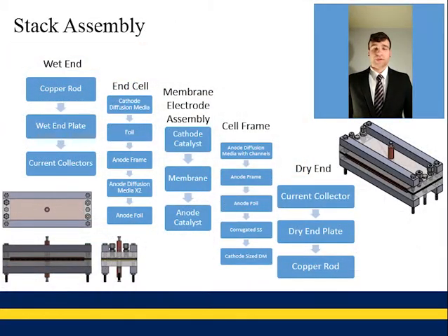So to create our stack, we actually needed to make several sub-assemblies first. At the very bottom, we have your dry end assembly, which is a copper rod, dry end plate, and current collectors fastened together. Above this, you have your cell frame, which is a cathode-sized diffusion media, corrugated stainless steel channels, anode foil, anode frame, and an anode diffusion media with channels cut into it for gas flow. Above this, you have your membrane electrode assembly, which involves an anode catalyst, your membrane, and your cathode catalyst.